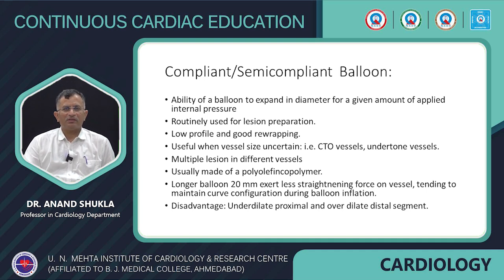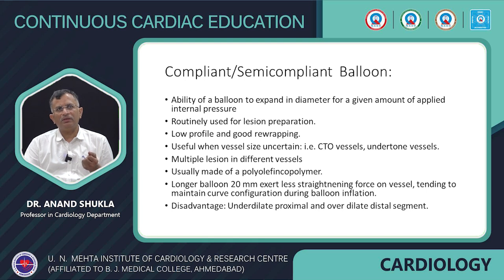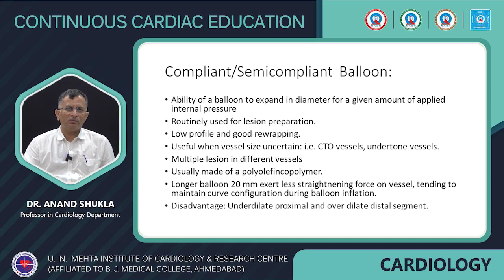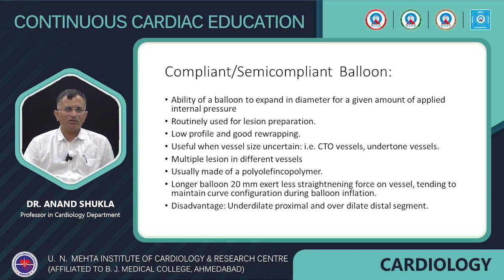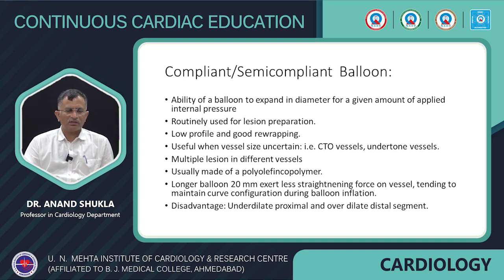Semi-compliant balloons are routinely used for lesion preparation before stenting. They are low-profile with good re-wrapping after deflation, and are useful when vessel size is uncertain — for example, when a CTO vessel has been opened and we don't know the vessel diameter. They are made of polyolefin copolymer. A longer balloon of 20 mm exerts less straightening force on the vessel, so whenever a longer balloon is used the vessel straightening force will be less, tending to maintain a curve configuration during inflation. The disadvantage is that longer balloons under-dilate the proximal and over-dilate the distal segment.